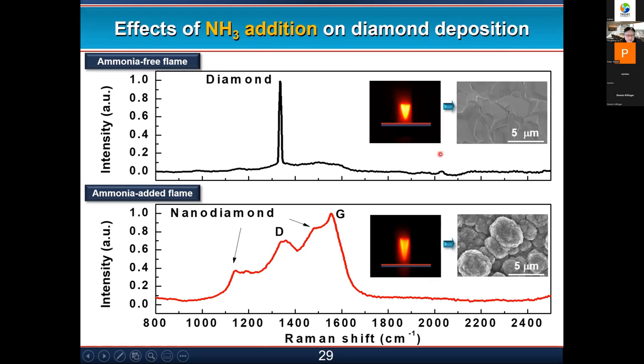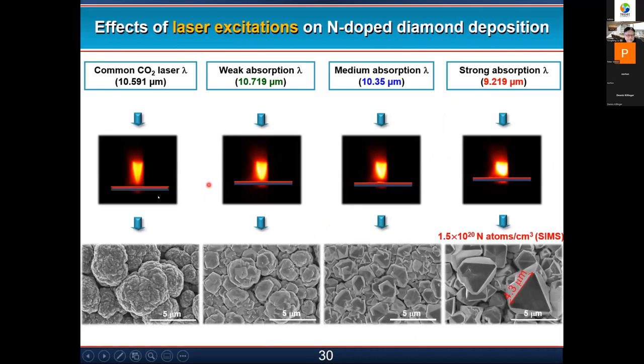Now, as we just mentioned, if we don't use laser resonant excitation, the diamond crystal will be reduced to amorphous or nanocrystalline material. You won't get a high quality crystallinity as we obtain in pure diamond growth. So what we can do is use resonant excitation at 9.219, and you can see that the diamond crystallinity comes back, with good diamond crystal structures, and also a very high doping level up to 1.5 times 10 to the 20 atoms per cubic centimeter.